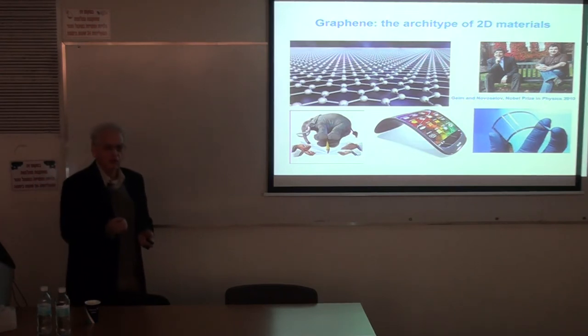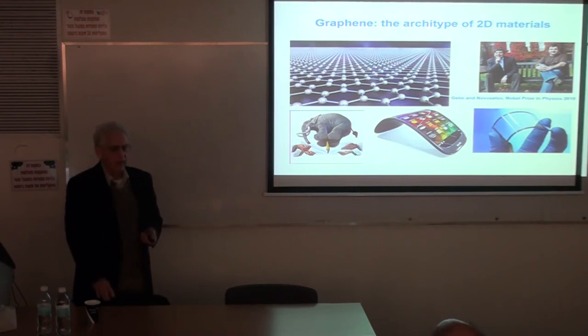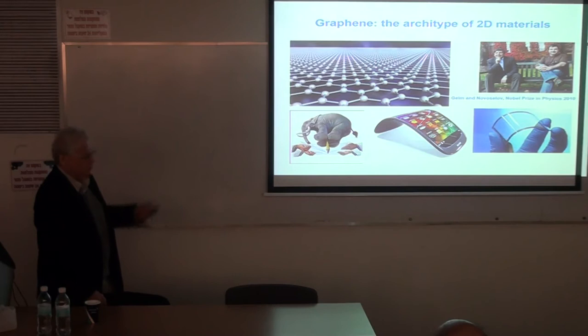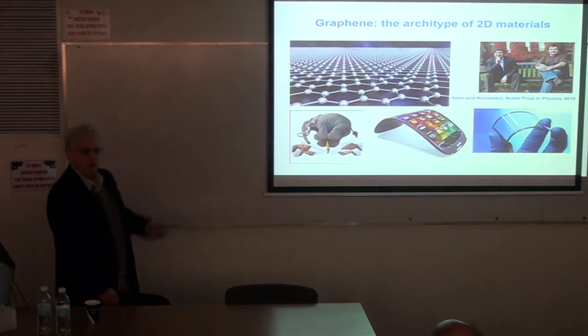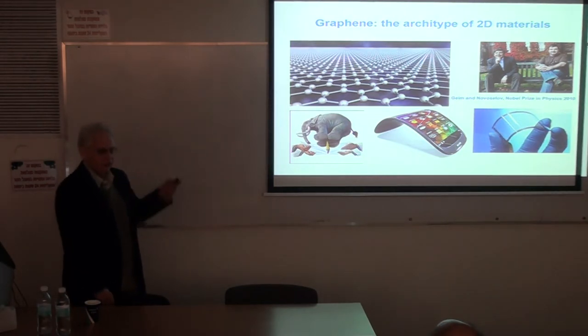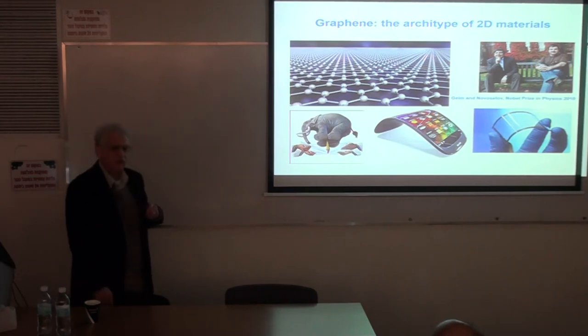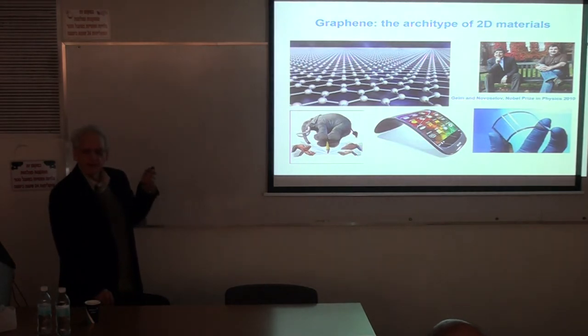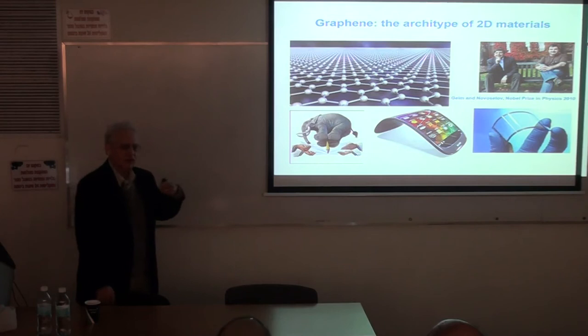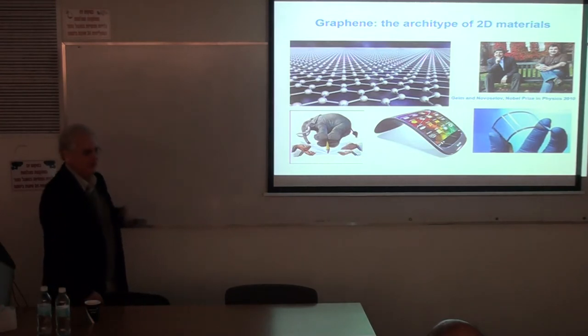The electrons do not obey the Schrödinger equation. In fact, they obey the Dirac equation, which tells you that the electrons are massless, and therefore their mobility is huge, and the conductivity is fantastic. And they have calculated a variety of physical constants, including the absorption coefficient of one layer of graphene, which is 2.3%, which is given by the fine structure constant, and they demonstrated that basically it's a translation of relativity onto a solid state material.